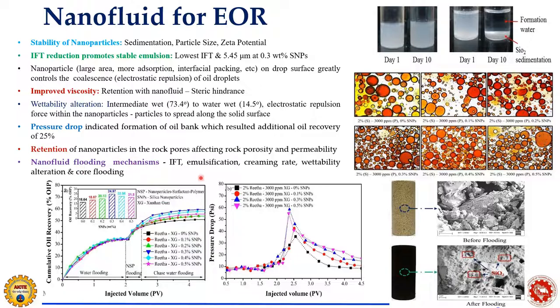Retention of nanoparticles in the rock pores affects rock porosity and permeability, as in the same case you can see in this image at the bottom right. So the nanofluid flooding mechanism, which includes surfactant and polymer, gives you a good reduction in the interfacial tension between the oil and the aqueous phase, good emulsification behavior with a good creaming index and low creaming rate, and wettability alteration changing from undesirable towards favorable. And finally, by core flooding, we could estimate the process by which you can recover around 25% of the heavy crude oil when you are implementing this natural surfactant.